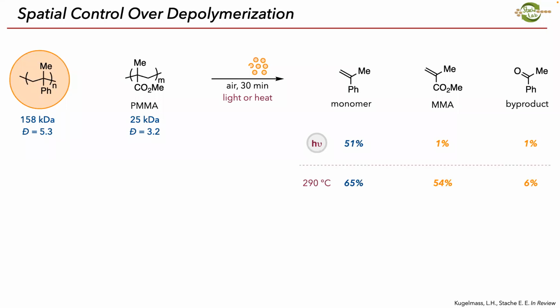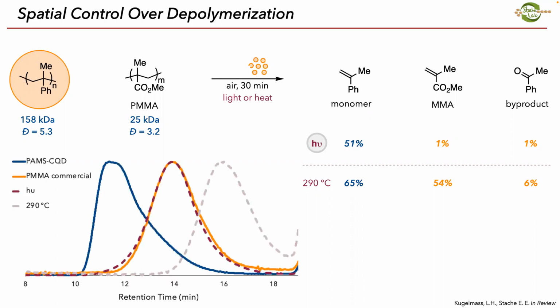However, if we heat this up to 290, now we get no selectivity for monomer formation. Both of those polymers are going to depolymerize, and we have to think about how we're going to separate those in a mixed product stream. And we start to see this oxidized byproduct. So this really shows that our photothermal catalysis method can give us selective and hopefully eventually iterative depolymerization of commercial polymers into clean monomer products.